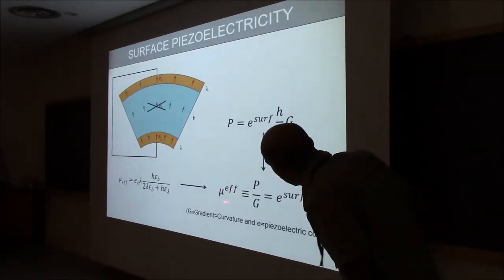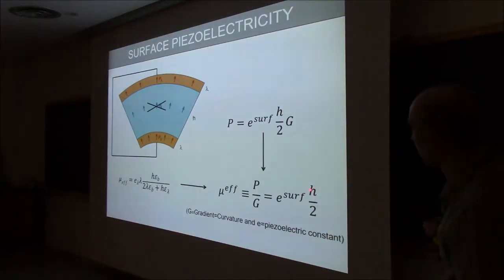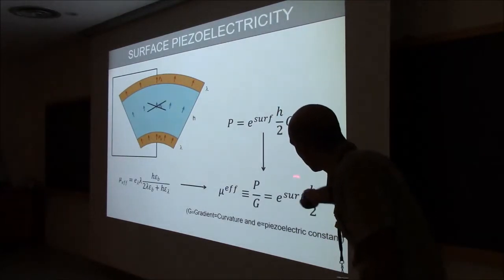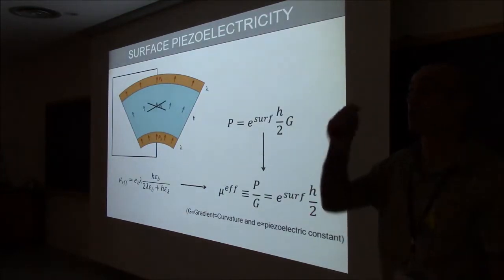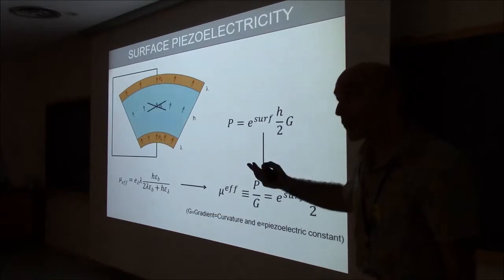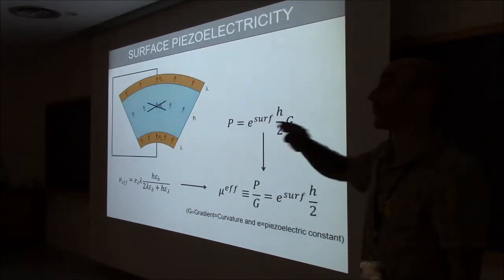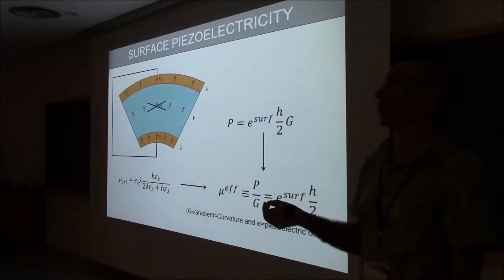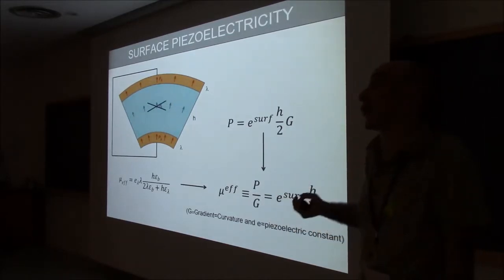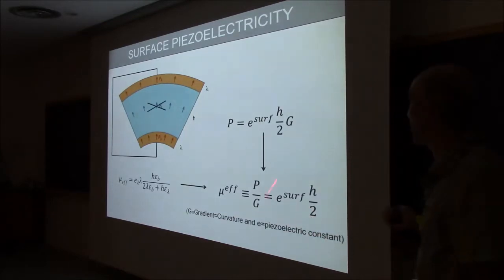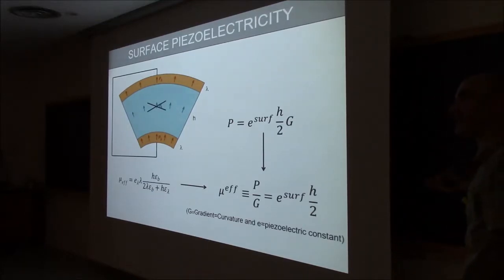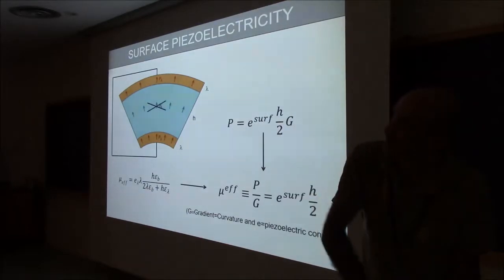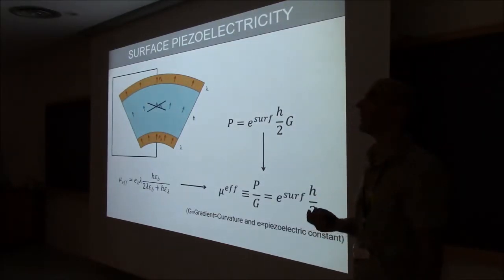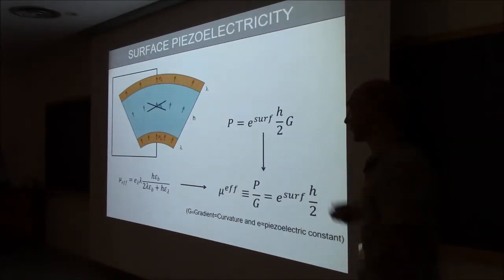And so now the surface piezoelectric contribution can be as big as it needs to be. And what you will find is that the effective flexoelectric coefficient is proportional to the piezoelectric coefficient of the surface times the thickness. So this flexoelectricity of semiconductors should scale proportional to the thickness of your sample. And in that sense, it's not a true constant because it depends on the thickness of your sample, but it can be big at the macro scale, right? Because this scale is proportional to the thickness. Whereas normal flexoelectricity is really only important when you go to smaller sizes. Semiconductor flexoelectricity is most obvious and manifests itself more strongly at the macro scale, which I think is kind of cool.